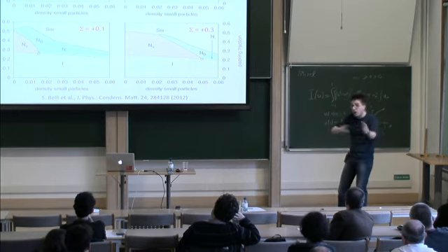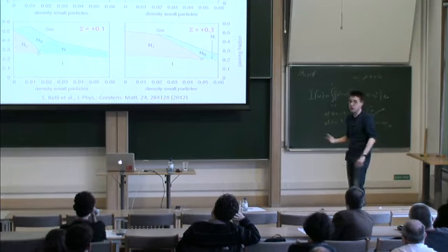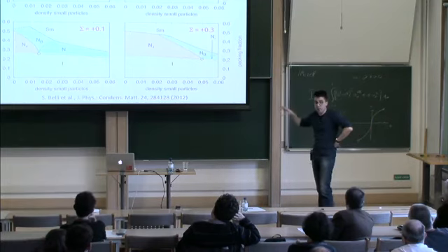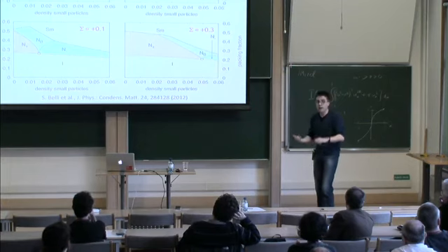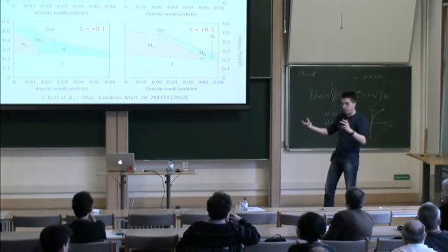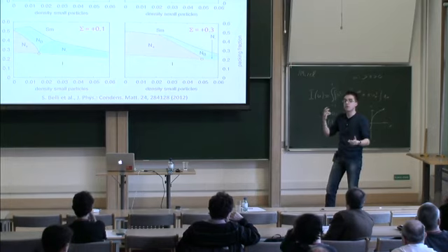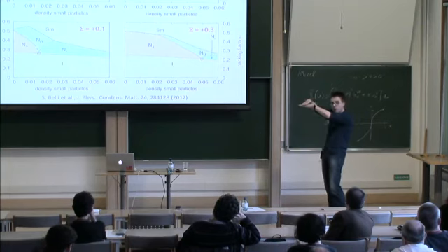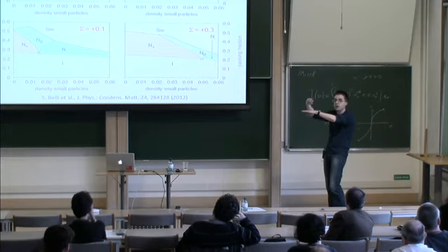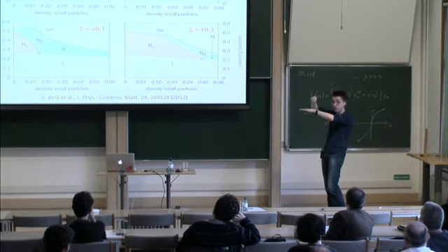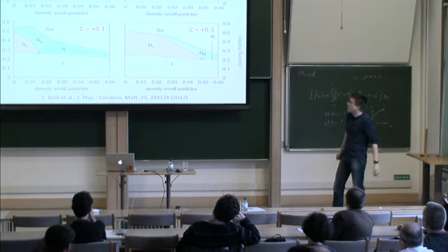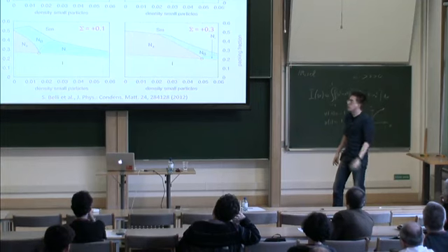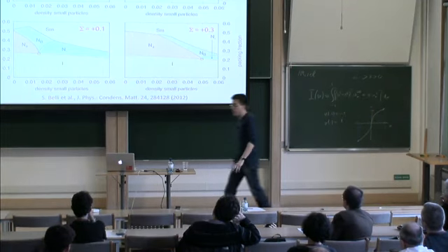And then we can change the perspective and go back to the binary mixture, and say that's probably the same thing that happens there, with the only difference that when the mole fraction of small particles is high enough, oblate ordering gives higher entropy, higher available volume for the small particles to occupy in the space. So it looks like the two models are related in terms of phase behavior.